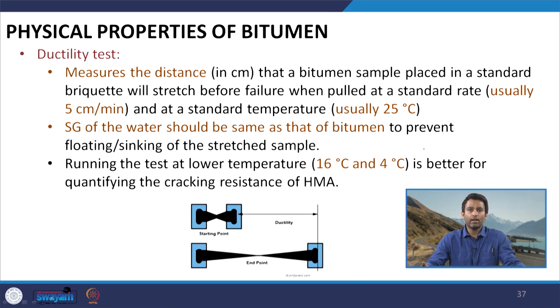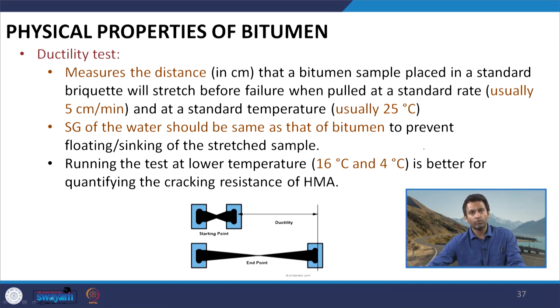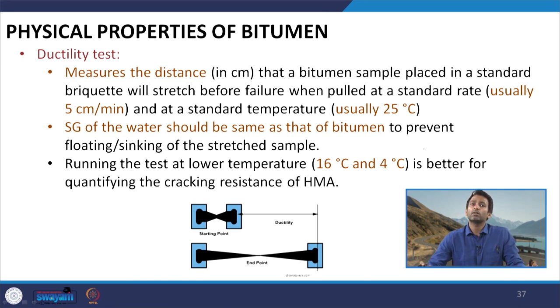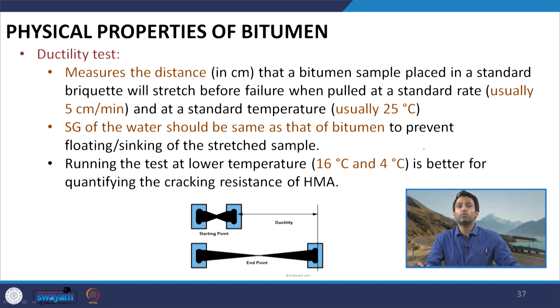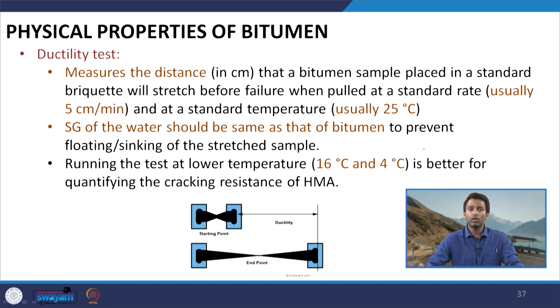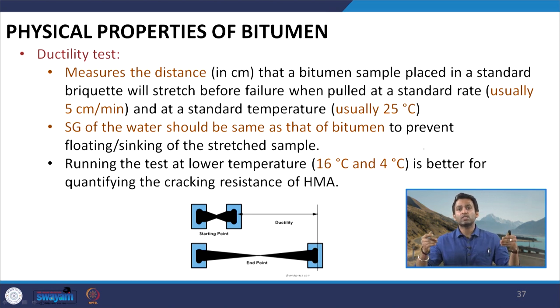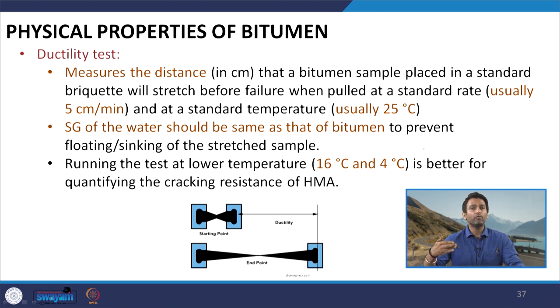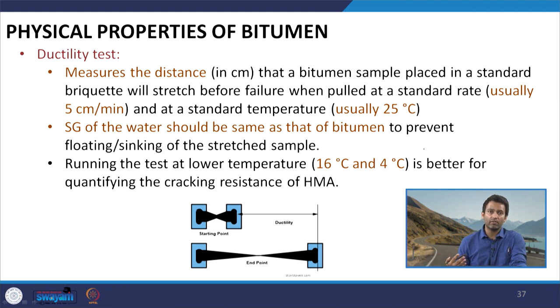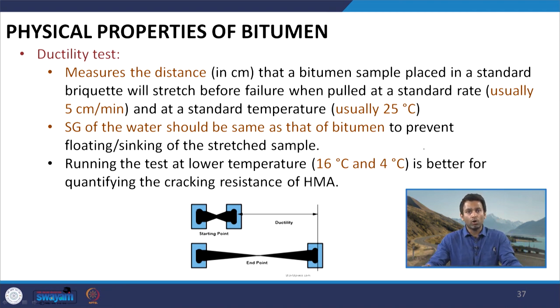This test is carried out under a water bath to maintain the uniform temperature of 25°C. An important point is that the specific gravity of the water should be approximately similar to that of the bitumen sample — this prevents the floating or sinking of the stretched sample. To increase the specific gravity if required, we can add salt; to reduce it, any form of alcohol can be used.